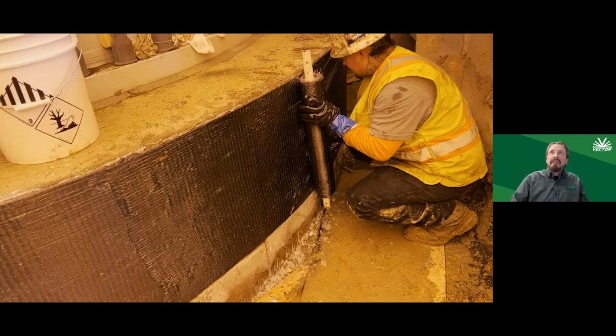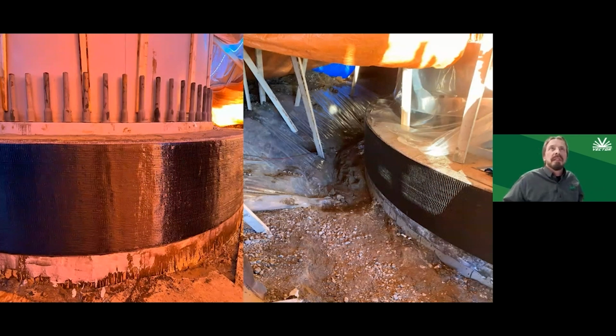So we saturated the fabric. Typically we'll use a dowel or a piece of pipe for very, very large pieces that are going to be installed. Get everything saturated, get it into the technician's hands so that technician can work with that fabric and get it installed. But you don't see in this photo, there are other technicians behind this installer smoothing down the fabric, getting rid of the bubbles, and making sure that it is as well adhered to the concrete and subsequent wraps as possible. So the final product is pretty simple.